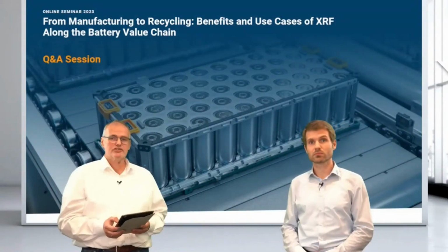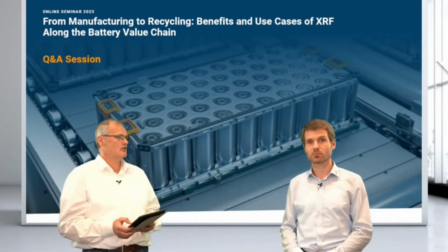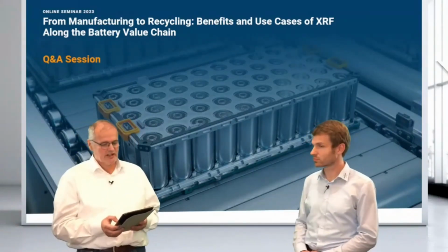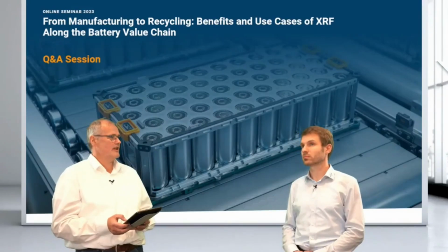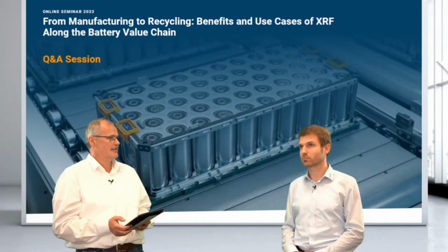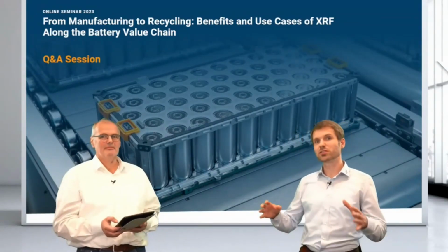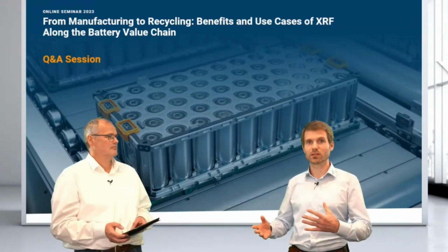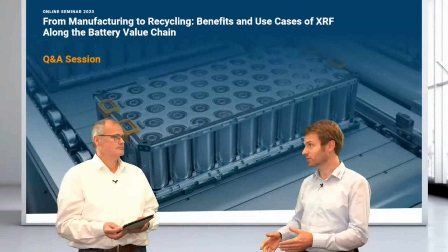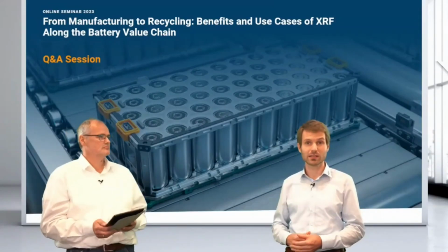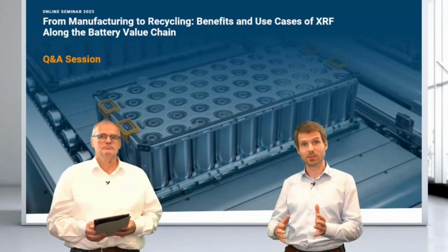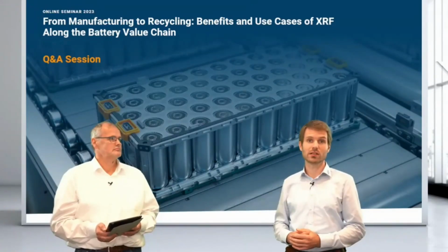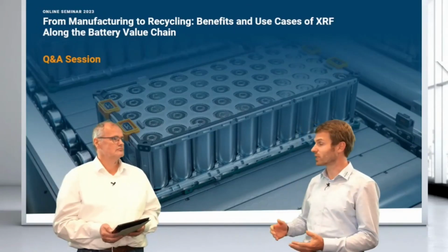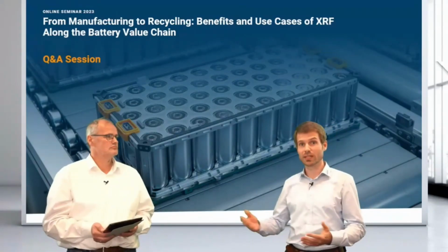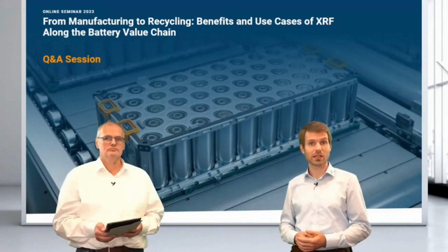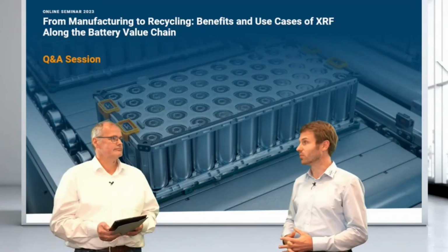One of the questions which was coming up, maybe from an XRD or XRM micro CT user: how to tackle cell chemistry when using XRF? Can you analyze elements directly in a cell? We cannot look inside the cell. So you can analyze basically every material that is going into a cell, the raw materials that are going to make the cell, and the precursors, like intermediate products, but we cannot look straight into a cell. There may be a few use cases where you want to cut a cell and look inside. The S8 Tiger has a mapping function, so this might be one of the applications where you can have a less destructive way, but it's rather rare.